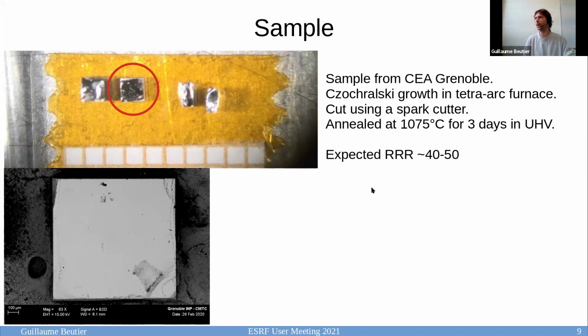But if you now look at the best samples which are grown by flux method, they go up to 300 or something like that. So it's much better. So this coefficient actually is a very good figure of merit because it includes chemical and structural defects that your sample can hold, which would affect the electric resistivity. So our sample is a cubic sample of 1 millimeter of size, and while looking at scanning electron microscopy, it's fairly homogeneous, I would say. I will come back to this later.